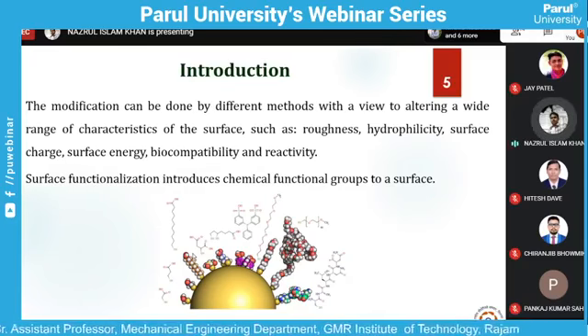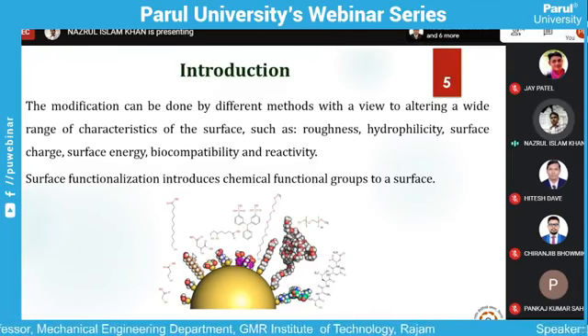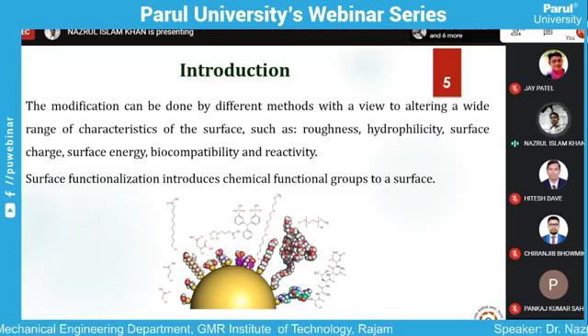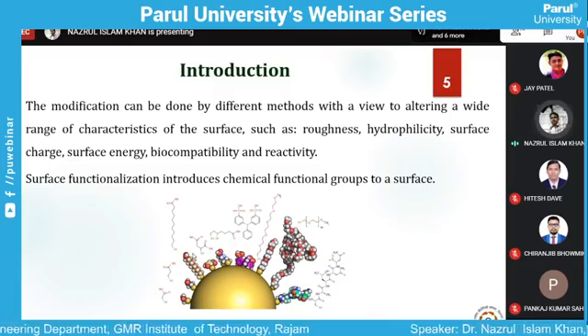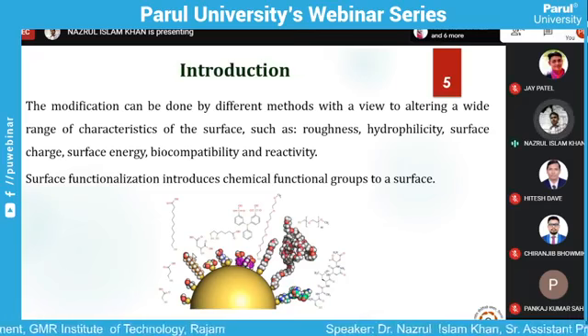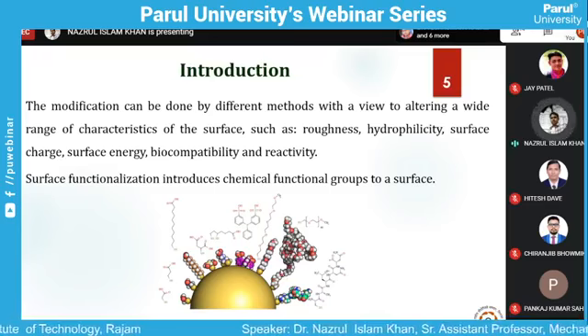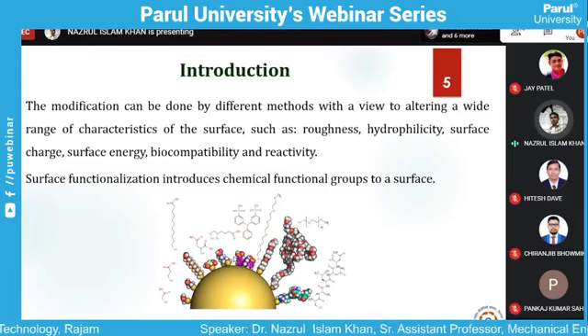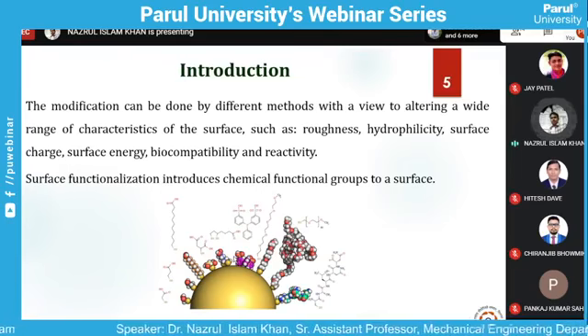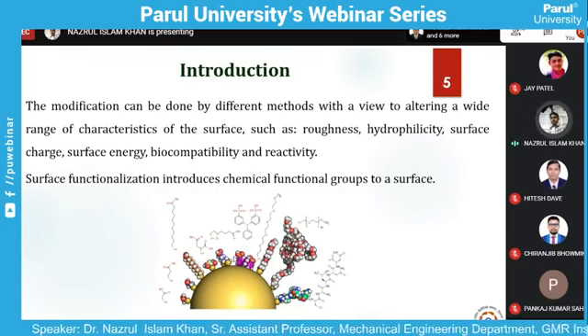So surface functionalization also introduces chemical functional groups. The easiest method, if you want to change the surface properties, is to select a chemical group to modify the surface functionalization. These are the technologies where a surface can be easily functionalized with different chemical groups. It may be a hydroxyl group, an epoxy group, a ketone group, or different functional groups as per our requirement. Suppose we need charge, then we need to go for free electrons and double bonds. Those things we can easily add on the surface of the nanoparticle.